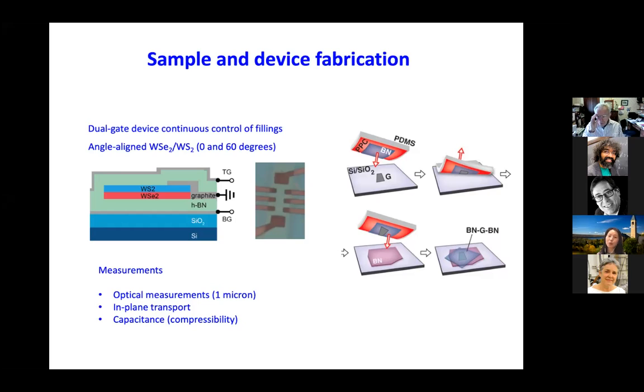The next step is we come in with a stamp like this. It's made of a polymer, and you can use temperature to control the softness of the polymer, so you can drop the whole thing or make it sticky to pick something up. This polymer has a boron nitride at its bottom, so the very bottom of it is also very clean. And this will come in and pick up monolayers one by one with very high precision, both in terms of position and angle. And now we have a whole stack of those things.